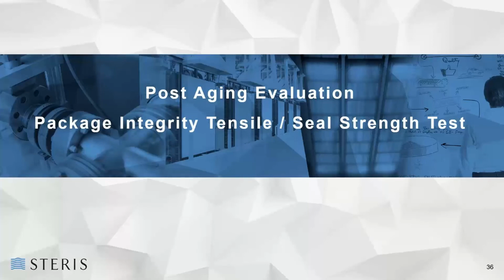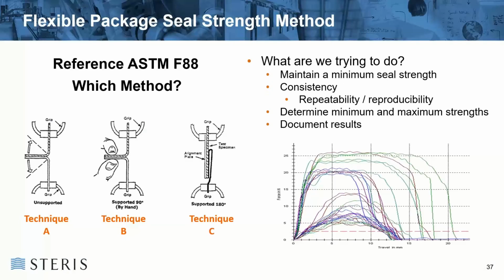If you look at the likes of the integrity or seal strength tests, the testing you're going to do will be the likes of the ASTM F88 standard, or alternatively the EN 868 Part 5 test standard. What you're trying to prove here is that you've maintained a minimum seal strength and that you have consistency, including repeatability and reproducibility of the actual seals after your aging processes.